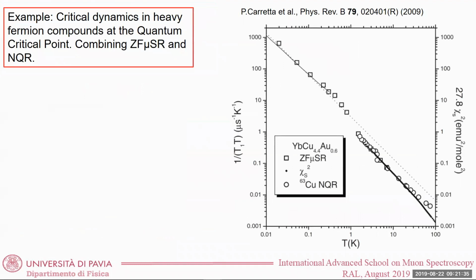Another example, this is a heavy fermion compound, which is very close to a quantum critical point. Again, also in this case, we started to do copper nuclear quadrupole resonance, so it's basically like NMR, but in zero field and associated with transitions between the levels split by the quadrupolar interactions. In any case, we measured 1/T1 on these nuclei, but we could measure it only down to this temperature, let's say about 1-2 Kelvin, because then the relaxation rate was too fast to be measured with a nuclear resonance technique. So what we did is to then go to PSI and to do the experiment.